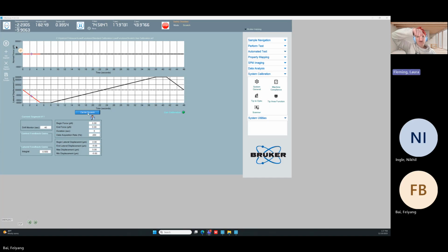Similarly, here for the scratch axes, we do not move in the normal direction. And instead, if we walk through this calibration, right, it moves back 5. That's that first leg where it goes in lateral displacement from 0 to negative 5. Then it holds, and then it goes from negative 5 to positive 5, holds, and then it comes back to 0. So 0 to negative 5, negative 5 to positive 5, so a 10 micron scratch here. Hold, and then back to 0. So during this long scratch, we know that the force felt should be 0. We're in the air. We're not scratching against anything. Just like in the normal indentation axis calibration, it's going to take that data, the spring data, know that it should be 0, and correct the electrostatic force to make that true.